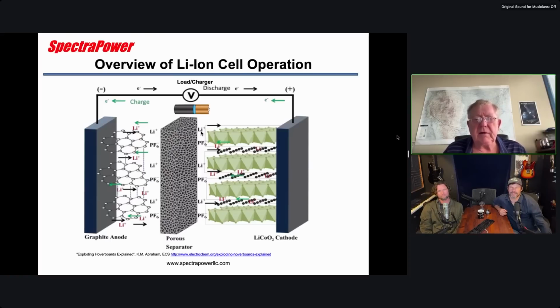Now, the electrolyte solvent, which is the basic solution, has mixed into it LiPF6, lithium hexafluorophosphate, which is lithium, phosphorus, and a lot of fluorine, 6 fluorines. Fluorine can be very, very hazardous, and one of the hazardous things in lithium-ion is it can combine with hydrogen and make HF, hydrogen fluoride, which is extremely dangerous. It will literally penetrate through your skin and dissolve bones. It's one of the things chemists are really scared of. It's very, very reactive, and so it's very dangerous. And the gas, if you breathe it, is also very dangerous.